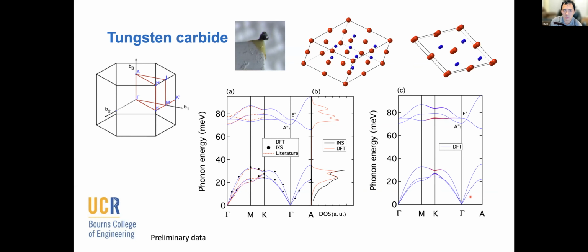As you can see, through most of the Brillouin zone, there isn't much phonon angular momentum or phonon spin per se, but near the K point, which is at the very edge of the Brillouin zone, we see purely right-handed and left-handed phonons. And those two phonons actually have different energies. So they are non-degenerate, with a small energy gap in between. So this provides us a good opportunity to probe the phonons there and see whether we should be able to see those phonon chiralities through inelastic X-ray scattering.